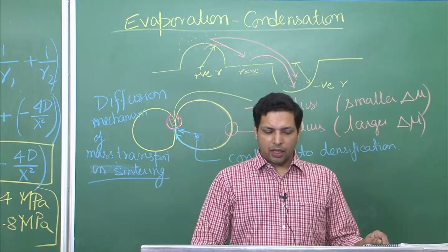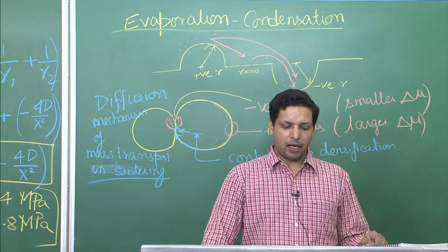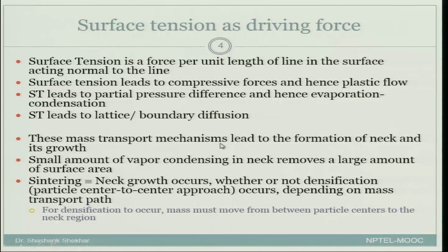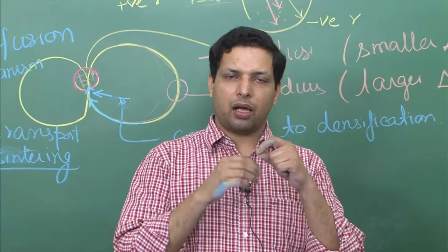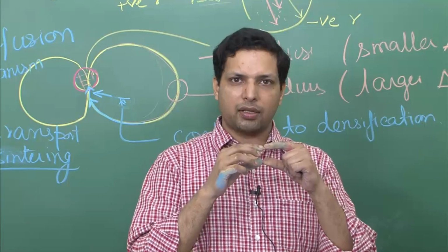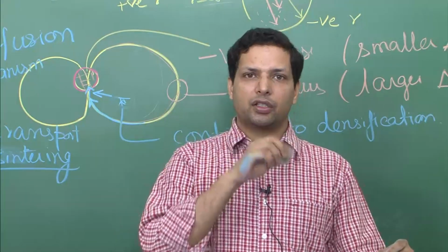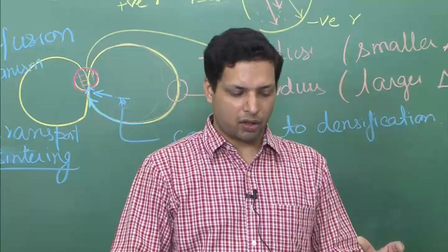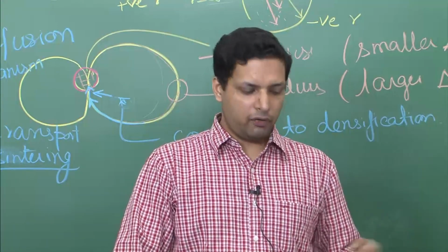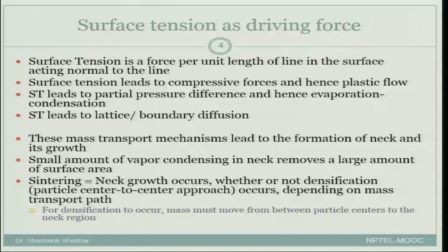So, what we saw, let us get back to our slide. What we saw is that these mass transport mechanisms lead to the formation of a neck and its growth. We also saw that with a small amount of vapor condensing, or in fact any other mechanism, you just increase the neck size by a small amount. Initially you have just a point contact, and then a little bit of additional material over there. So, neck size is increased by just a small amount, but the surface area decreases by a very large fraction. That means that initially you will always have a much higher rate of sintering.